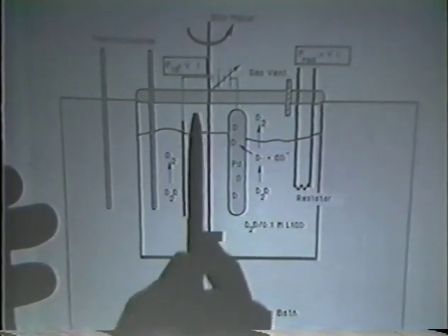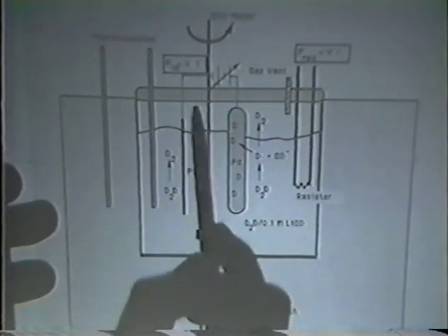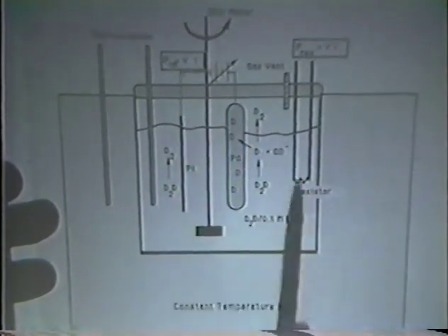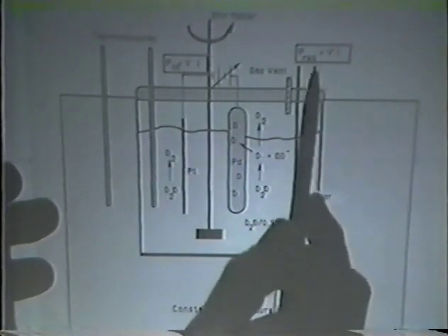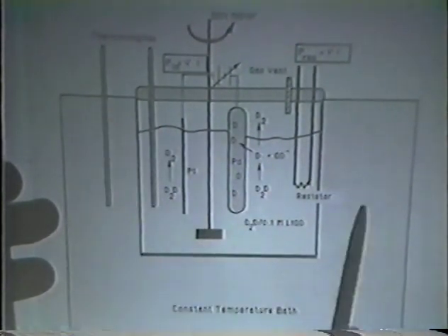We use the same method generally as the MIT people have used, where you put a given power through the electrolytic circuit. You have a power that's also gone on through a calibrated load resistor to maintain a constant temperature of the system relative to the bath.